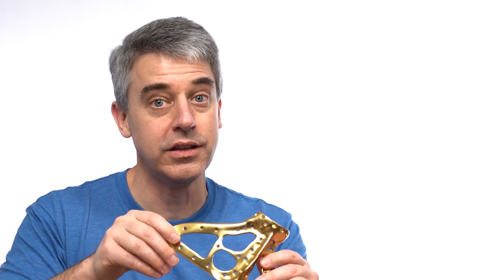In this case, 3D printing this implant wasn't all that difficult — there were no significant design changes necessary. The design of this part from an orthopedic perspective doesn't require a lot of modification when leveraging electron beam melting. One unique aspect of EBM is there's really no distortion in your components because it's done under vacuum at elevated temperatures — no localized stresses are created, and there's no stress between the platform. We can actually float the part above the platform.